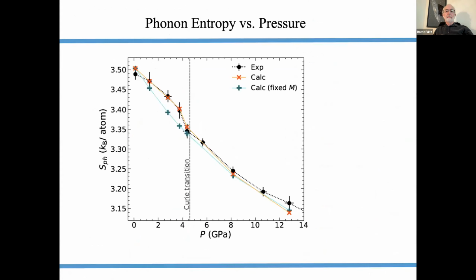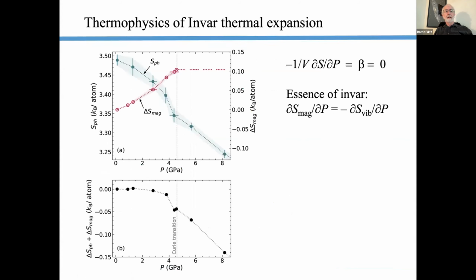All right, here's the phonon entropy versus pressure. This is falling because we're getting stiffer phonons and the atoms don't move as much, so the entropy goes down. And our experimental points are these up to the Curie point, then it gets kind of flat above that. The theory group was able to turn on and off the spin-phonon interaction, and so they actually got an explanation for this curvature behavior here, claiming it's related to how the phonon is affected by the spin disorder in the system. But this is the essence of INVAR right here.